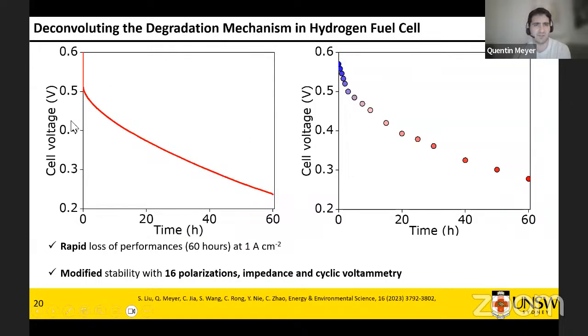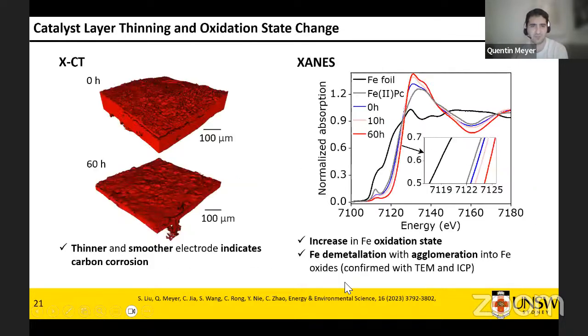So the best way to figure out what's happening is to try to isolate it. So this is the stability of a catalyst over 60 hours. As I was showing you earlier, with this catalyst you could say, oh, that's not very stable. It's actually very much middle range of stability for a cathode. So perfect for our study. It's middle range compared to the other materials in the field. And what we've done is we basically try to freeze this stability by taking measurements at different points as the cell degrades. And so we captured the state of the cell using polarization curve, impedance and also cyclic voltammetry, which I'll get back to. But before we did that, we did a bit of physical characterization.